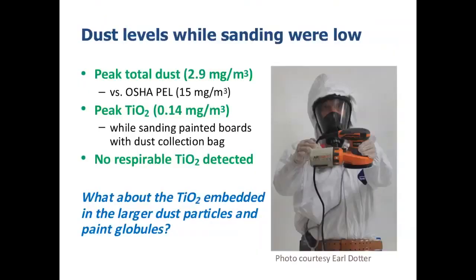So this was despite the fact that dust levels during sanding were actually quite low. The highest concentration of total dust during sanding was about 5 times lower than the OSHA permissible exposure limit. And for titanium dioxide, the highest breathing zone concentration was detected while sanding painted boards with the dust collection bag shown on the right of this slide. But there was actually no respirable TiO2 that was detected while sanding.